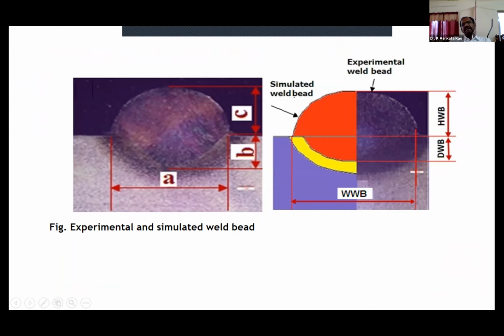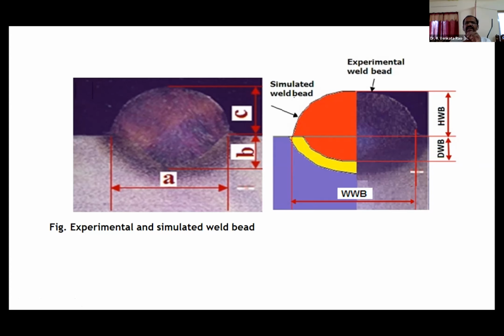Second figure is the simulated weld bead, compared with the experimental weld bead. So the two figures were joined there. We can say the width, depth and height of the weld bead are the same as the experimental weld bead. The error is less than 5%, it is not a considerable amount. So we compare the experimental and simulation results, and they are almost the same, almost the same as the experimental weld bead in the second figure.